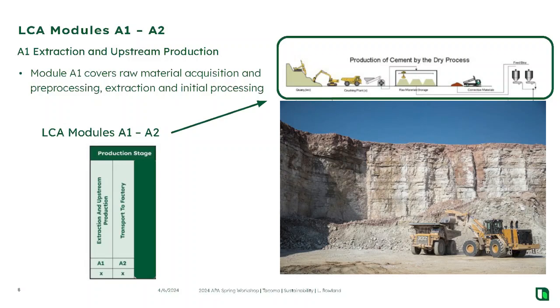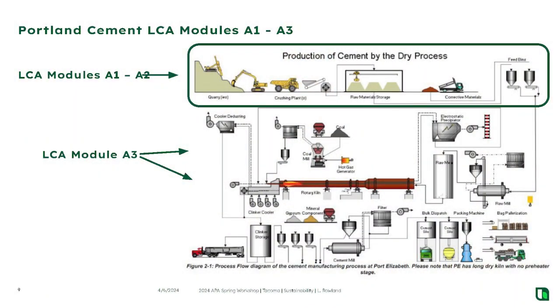For cement, it's my A3. That's my big impact, is in my manufacturing process. I take those raw materials, I grind them up in my raw mill, and then I put them through the kiln. About 25% of my emissions are the fuels I burn, right? I have to raise those temperatures up to 2,800 degrees or so. And then the CO2 that's released from the limestone, the calcination of the limestone, in this case, for this specific cement, is about 63%. It's about 2/3 is what we say. 60 to 70% of all the CO2 emitted from the cement comes from that chemical process.